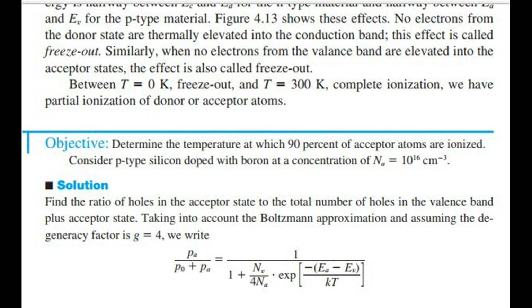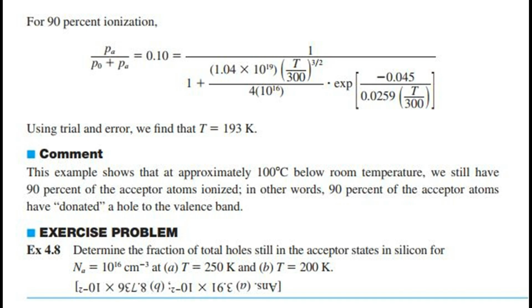Consider p-type silicon doped with boron at a concentration of Na = 10^16 per cubic centimeter. Solution: find the ratio of holes in the acceptor state to the total number of holes in the valence band plus acceptor state. Taking into account the Boltzmann approximation and assuming the degeneracy factor is 4, we write for 90% ionization. Using trial and error, we find that temperature equals 193 kelvins. Comment: this example shows that at approximately 100 C below room temperature, we still have 90% of the acceptor atoms ionized. In other words, 90% of the acceptor atoms have donated a hole to the valence band.